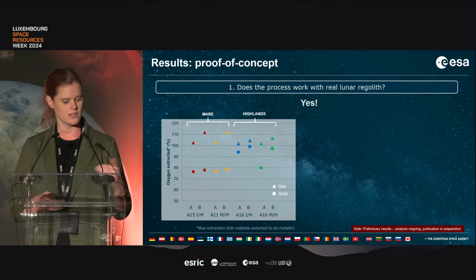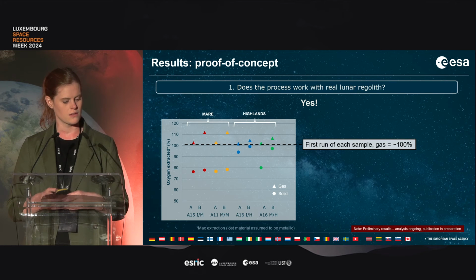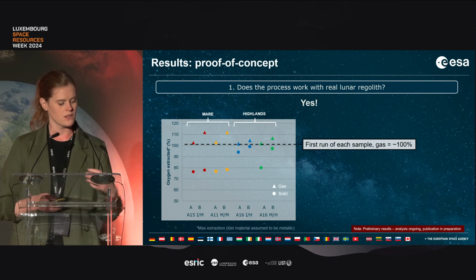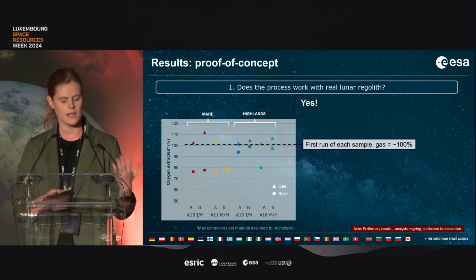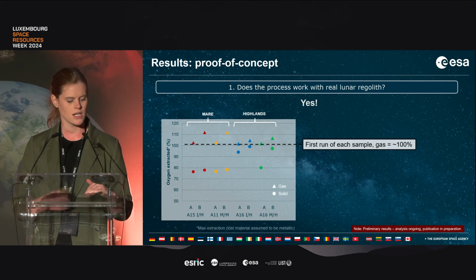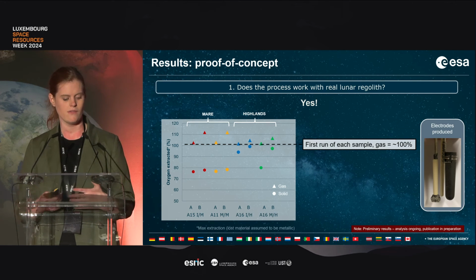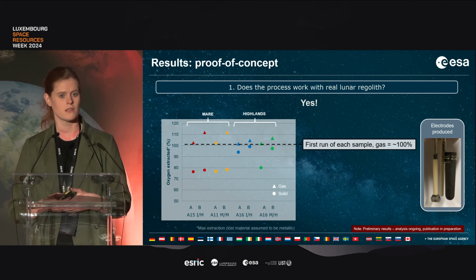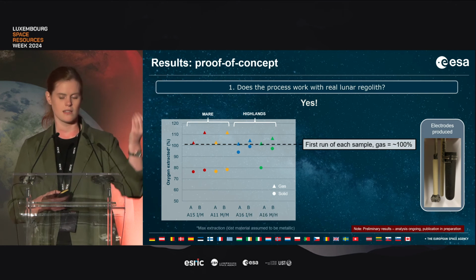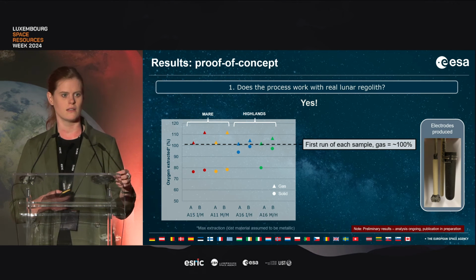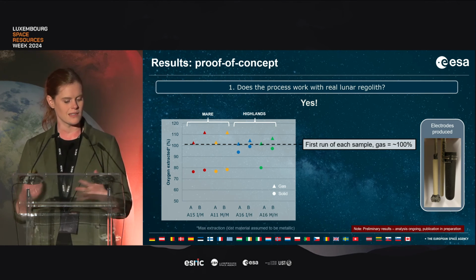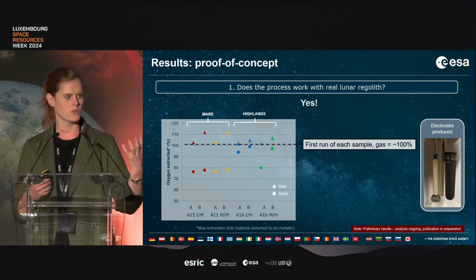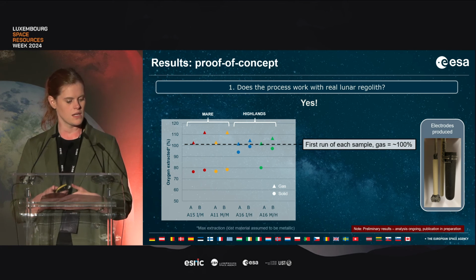So what we can see is there's a bit of a discrepancy between those data points. For the first run of each sample, for sample A, we ran to around 100% gas extraction. However, we do have other oxygen sources within the experiment. Here you can see the alumina sheath that's on the rod of the cathode. This was necessary in such a tiny system to avoid any short-circuiting between the rods. But yeah, that was another source of oxygen in the system.